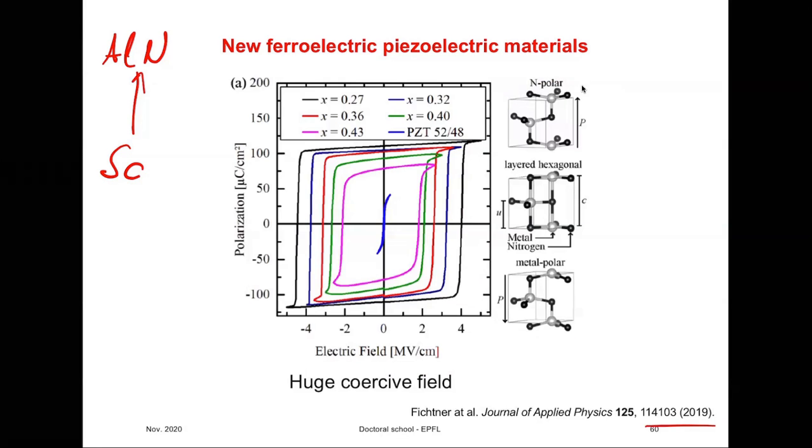This is still very interesting from a scientific point of view, that we can induce ferroelectricity. And second, from the practical point of view, sometimes when you make aluminium scandium nitride, these grains will grow in a columnar structure, but the distribution of polarization up and down would be about 50%. So you get very low piezoelectricity if you don't grow it carefully, if you don't control nucleation carefully. Now that we know that they are ferroelectric, we can apply electric field, and these sort of coercive fields can be easily reached in thin films. These materials shouldn't show high conductivity, and this might be possible.